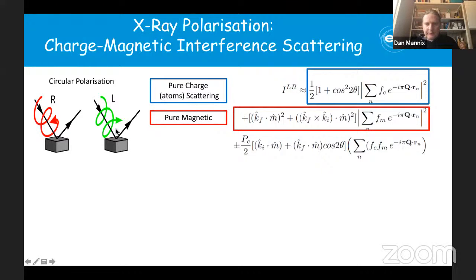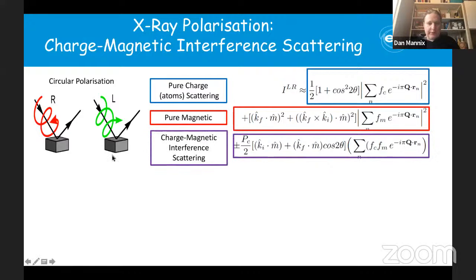We'll go into a little bit more about those later, but there's a final term, which is the one that we've actually been using. This is called a charge magnetic interference term. This is the one that was important in our measurement of this nanodiffraction. We've been exploiting this term, which gives a strength which is related not just to the FM term, not just the magnetic one, it's the FM term multiplied by the FC term. So it's actually stronger than the pure magnetic term. Not only that, it depends on the helicity of the light. So if I come in with left or right light, this polarization helicity term will either be positive or negative. So this term can be isolated in circular light just by taking the difference between left and right.